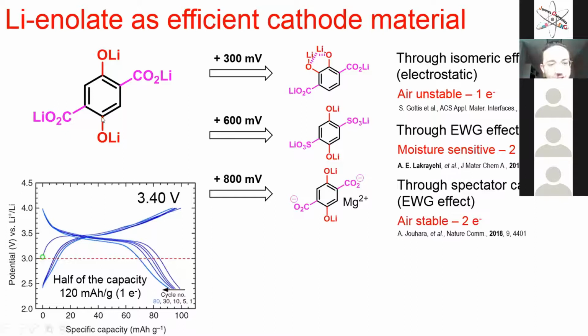After that, you keep the same molecule, which is I would say the reference, and you substitute the spectator metal cation. Here, instead of putting lithium, you put magnesium, for example. By doing this, you will change the electron density of the carboxylate. It will become very low, and this will increase the potential. Here we have a huge increase of the potential, almost 800 millivolt, and you have a material that can react at a potential of 3.4 volt, which is air stable and moisture stable. So it's very, very good.